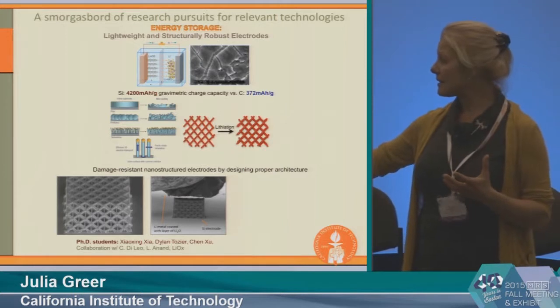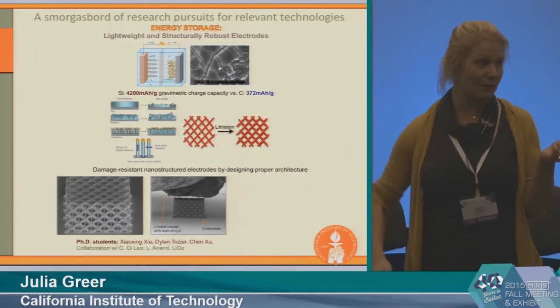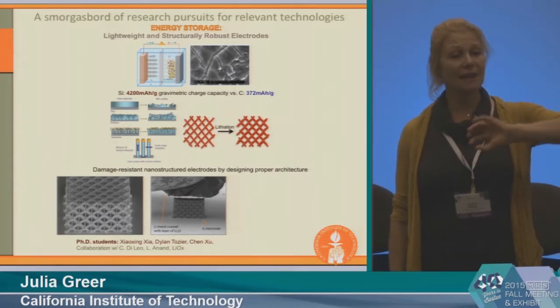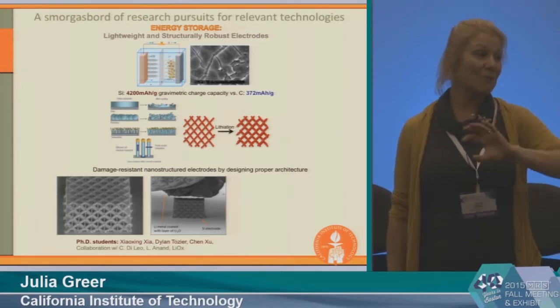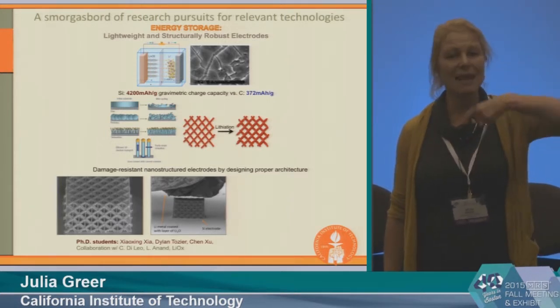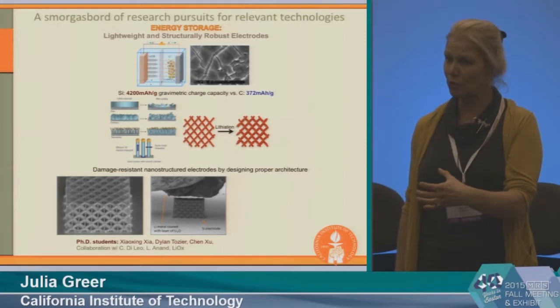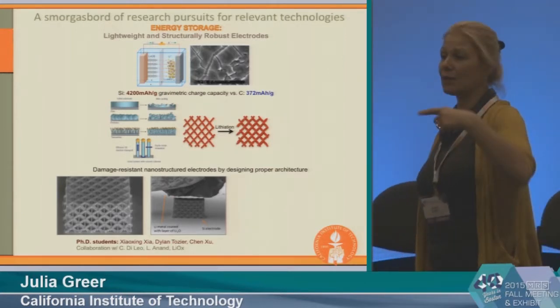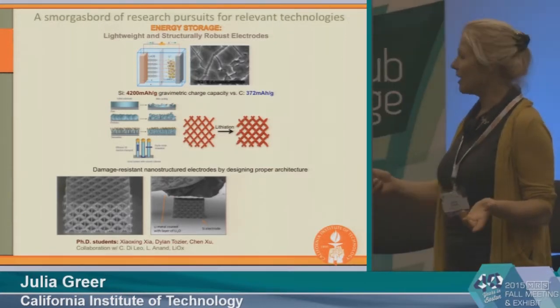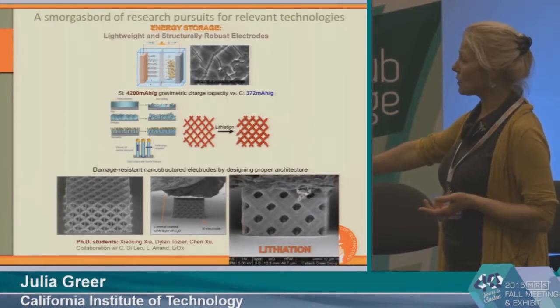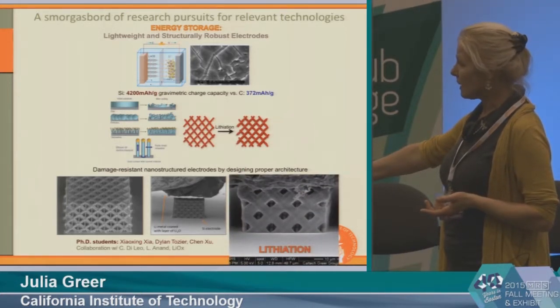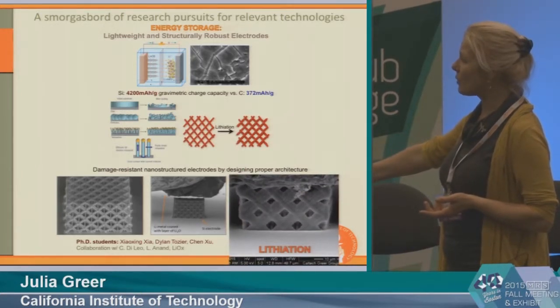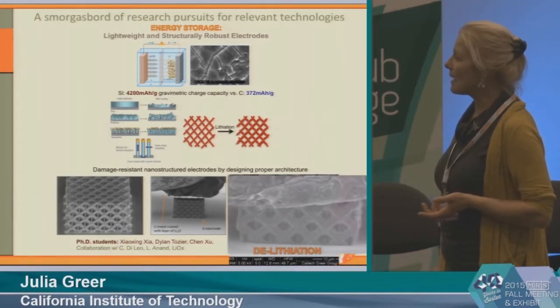So this is an anode, a silicon anode made for a lithium-ion battery. The entire thing, instead of being hollow, is now made entirely of copper with a silicon nanoribbon wrapped around it. So the copper is your electron conductor, and then the silicon, of course, is your ionic transport material. And what you can see is my student Xiaosheng lithiating it, so you can see the lithium ions going in and then the lithium ions going out.